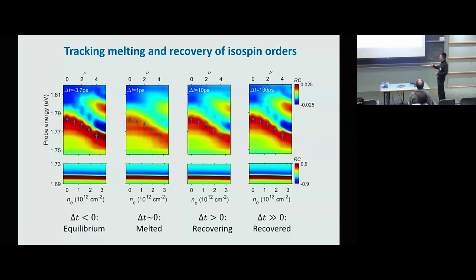And I think it's probably not completely true that this cascade feature is directly related to isospin order. They are related to isospin order, but not necessarily a direct signature. For example, this is not a gap. It looks similar to the chemical potential measurement previously, but you can see these cascade features even above the ordering temperature. So they are not really a one-to-one correspondence with the isospin orders, but they are connected.